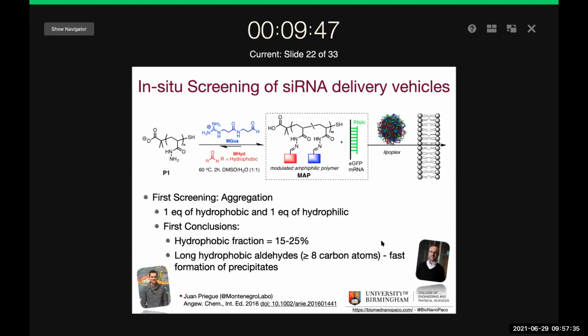And actually, again, the chemistry is quite simple. Like I say, we tend to use a little bit of organic solvent to dissolve those hydrophobic aldehydes. But depending on the assay, this is not a big problem. You know, it often gets diluted down when you add your nucleic acid of interest, and this is siRNA. And sometimes you will even get further diluted when you put it into your cell assay, right? So, you know, at the end, you may get less than 1%. And I think in this assay in particular, we were using 0.01% of DMSO. We now have ways of using other solvents that can be removed, right? So they are not present when we use them.